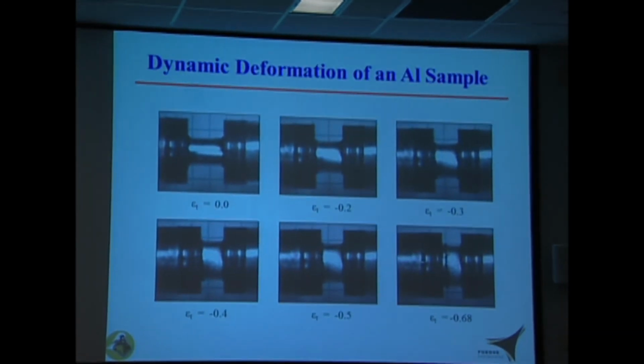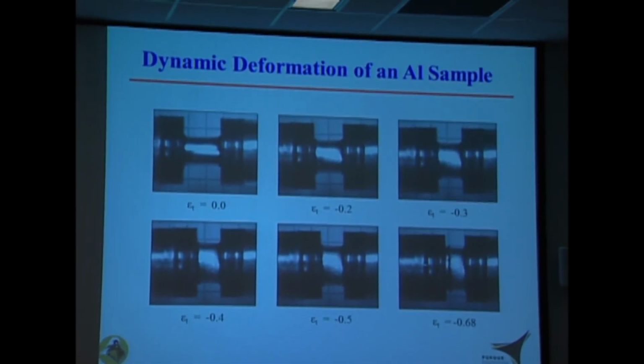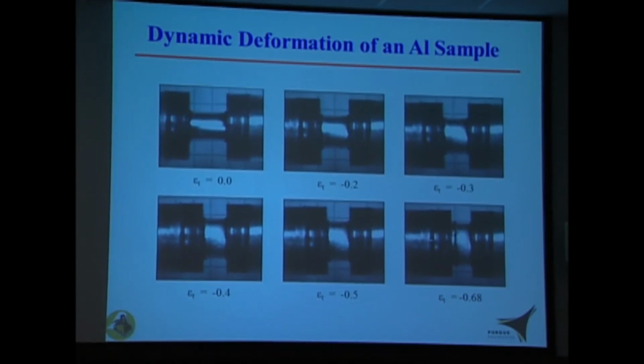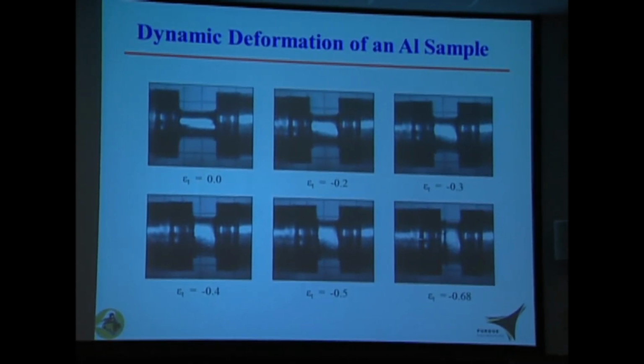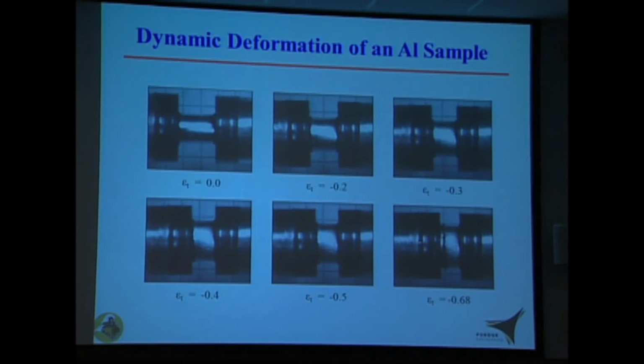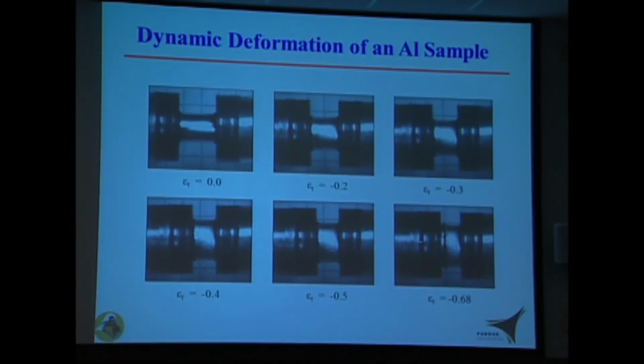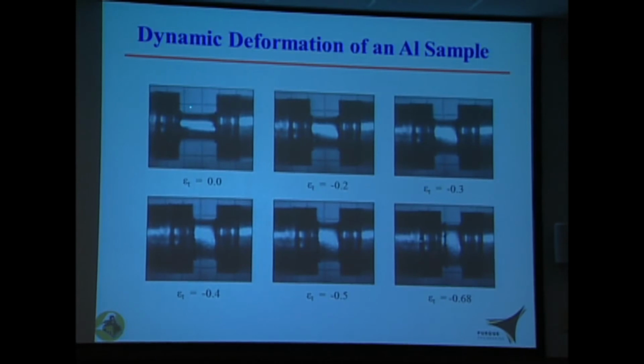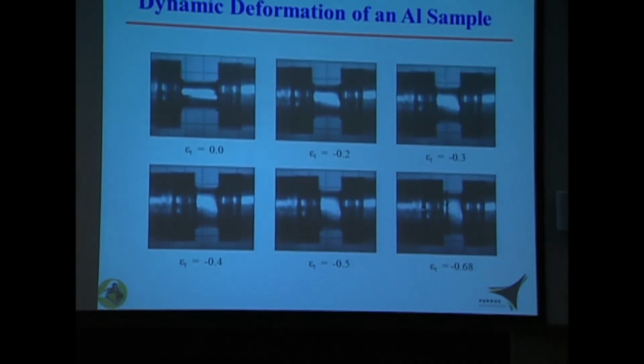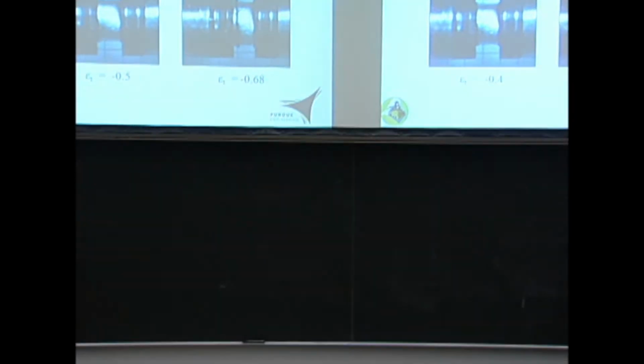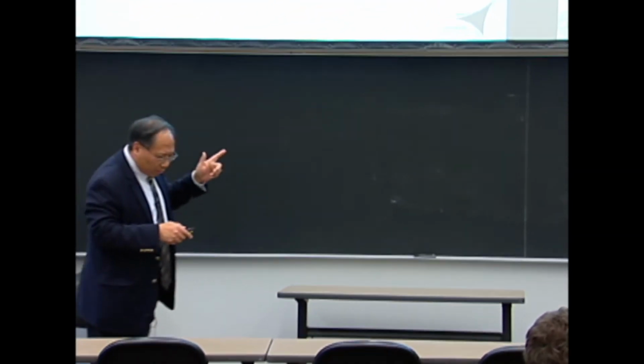drum out. And I was requested by a group that does very high deformation analysis. So they want the sample to deform to very high strain without drumming. So you see this is the sample starting with a flat surface, even to very, very high strains. The edge remains straight. It never drummed down.